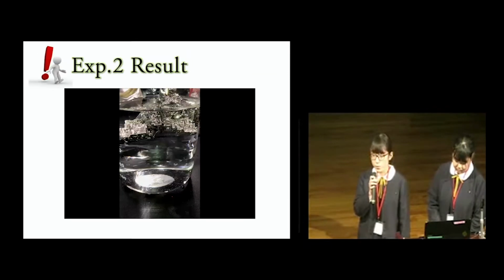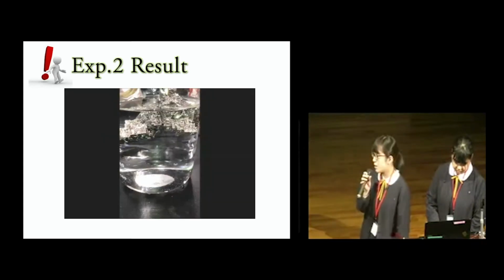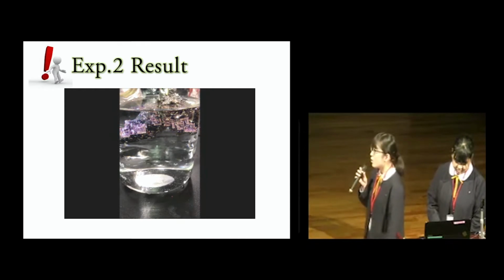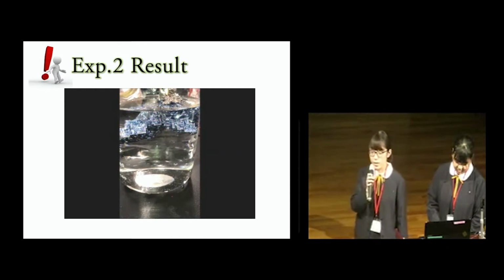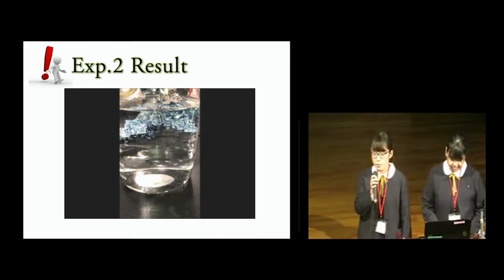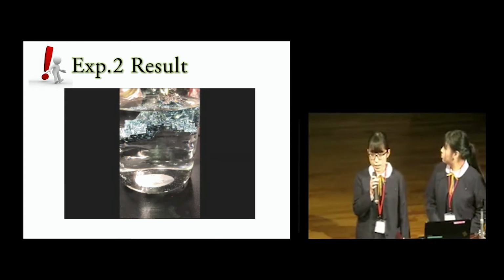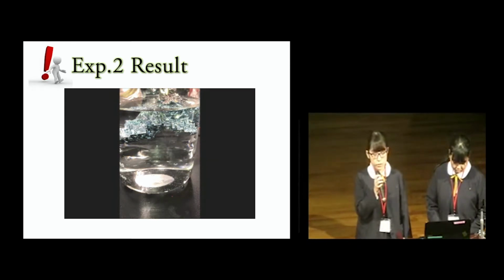We recorded the process of oxidation of bismuth crystals by anodic oxidation. Please take a look. It can be confirmed that the surface color of the bismuth crystals changed to gold, blue, light blue, and magenta as the current flows. We have experimentally found that the color of the crystal once again becomes gold, blue, and so on when the surface of the crystals is oxidized.